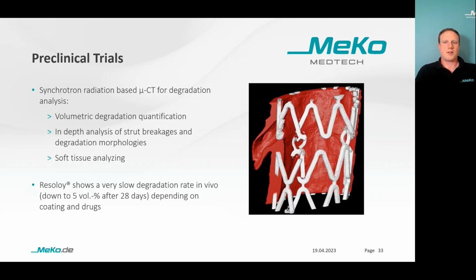To track the degradation kinetics in vivo, MeKo has access to a synchrotron-based micro-CT analysis, and with this technique we are able to generate a deep understanding of degradation kinetics and degradation morphology in vivo. On the right you see a reconstruction of an in vivo degraded Resoloy scaffold. And as you can see, not only strut breakages are visible, but also the soft tissue, and several degradation products can be tracked.